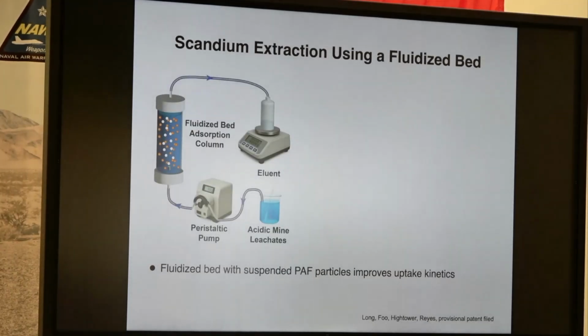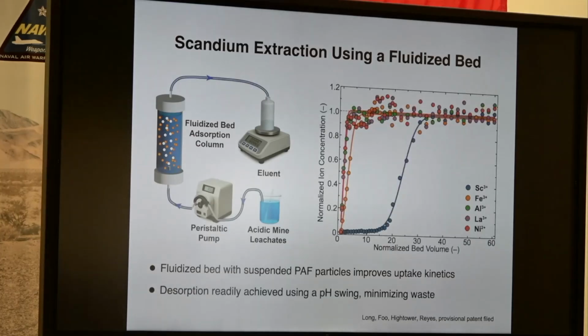If you're going to use these, the best way to do this for getting fast contact with the metals is in a fluidized bed instead of a fixed bed where the particles of the polymer are fixed. We're going to suspend the particles in a fluid in the incoming water stream, aqueous acid, and they're going to capture. This is a breakthrough curve. This is just showing that only scandium will stick to that column or that material in the fluidized bed. Everything else that we tested comes through. Once we've saturated, we can release scandium just by changing the pH. A pH swing releases the scandium, and then you can use the adsorbent again.